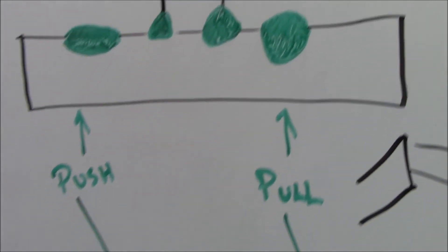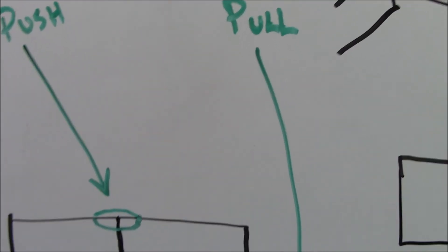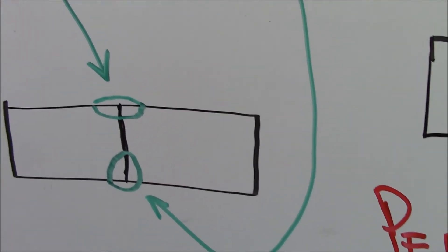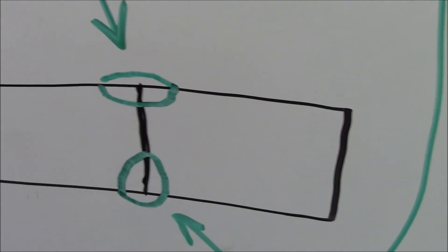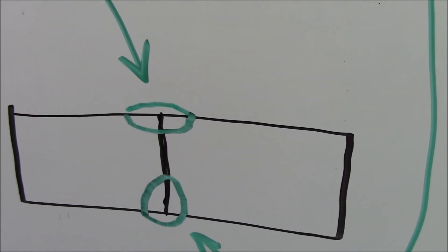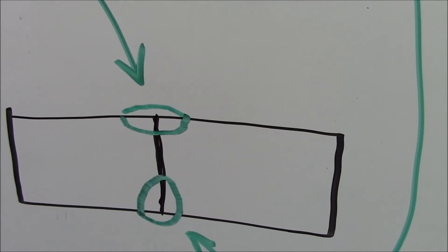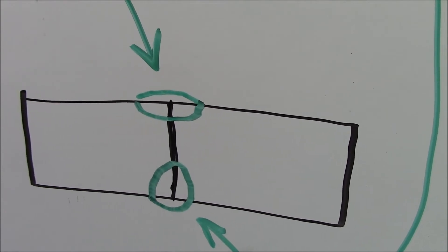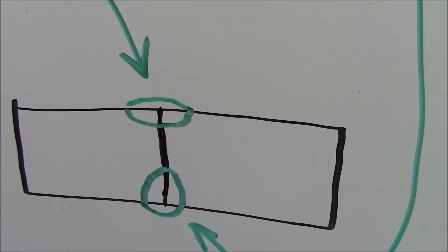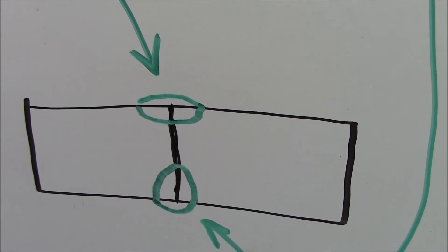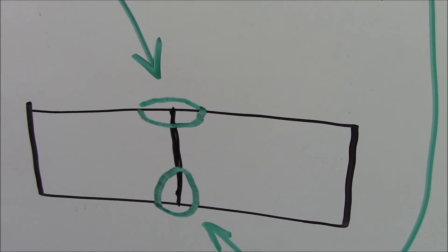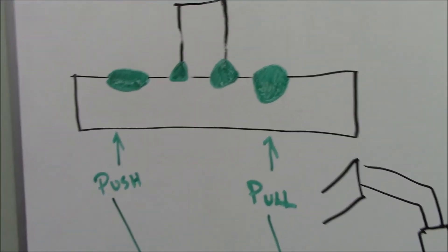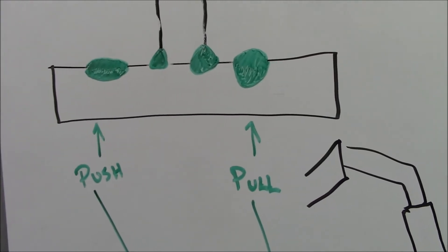So, then, what does that mean for penetration? Well, when you've got, say, like a butt joint, a square groove butt joint, the push is on top here, and you can see you're just getting fusion, you're just not getting the penetration. Whereas, on the bottom, that would be what you would see if you were using a pull technique. So, is there a right or wrong? It's really just application-based.